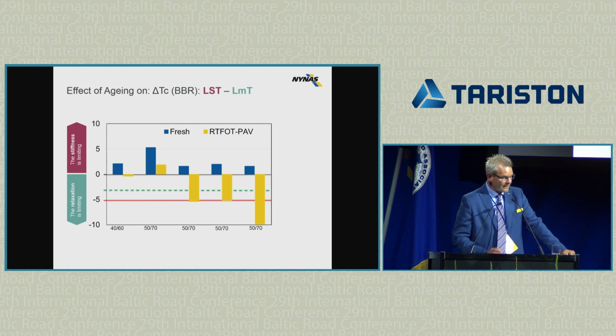And you can see that there are remarkable differences in delta TC. I've drawn 2 lines, a green line, which is minus 3 degrees, and minus 5 degrees. The minus 3 degrees corresponds to the notion from the field that is where bitumen starts to crack. The minus 5 degrees, if you are below minus 5, there is serious risk of bitumen cracking in the pavement.